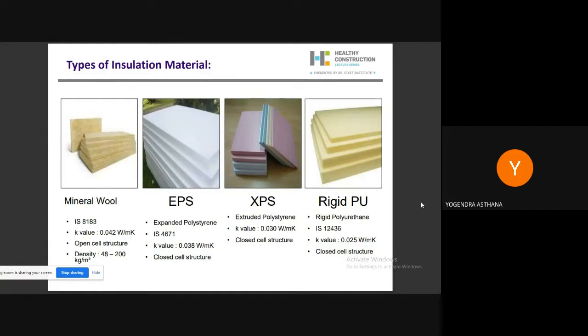As we mentioned, there are different materials in different categories. Mineral wools have a K value, thermal conductivity value, of 0.042, whereas expanded polystyrene boards have a K value of 0.038. The lower the K value, the better the insulation efficiency of the material. Then XPS boards have a K value of 0.030, and PU foam, polyurethanes, have a K value of 0.025. So we can see that polyurethanes are more efficient in giving thermal insulation to the structure against mineral wool, EPS, and XPS. All these are used, but the most efficient material is polyurethane foam. So next slide, please.